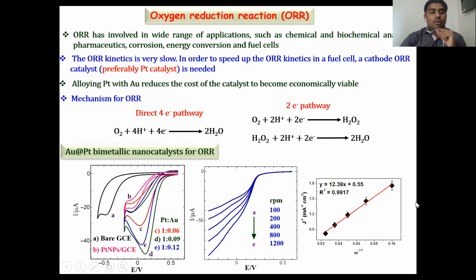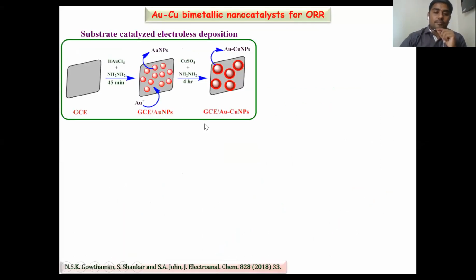Here we utilize the gold platinum bimetallic nanoparticles fabricated electrode for the O2 reduction, and the bimetallic nanocatalyst exhibited higher catalytic activity by reducing the onset potential as well as the overpotential of O2 reduction, and with the enhanced reduction current. Moreover, for different RPM, we have analyzed with the RDE, and with the help of the Koutecky-Levich plot, we found it is a 4-electron transfer mechanism, and the mechanism is O2 to water.